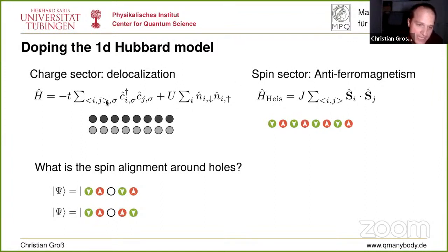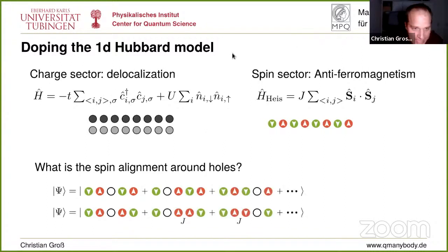You can do that by having antiferromagnetic correlation across the hole, which is, by the way, opposite as if there would have been a downspin, right? If there would have been a downspin, those distance 2 spins would be aligned, but if there's a hole, they are anti-aligned. Why? Because then you can delocalize the hole and you never pay an energy.